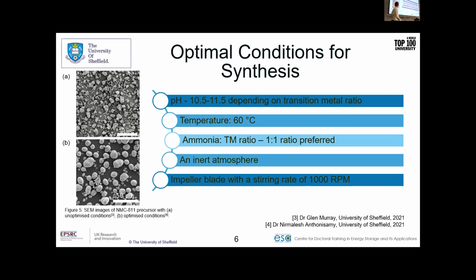And finally, in order to ensure that we provide enough shear forces to prevent clustering of these spherical particles, we like a nice impeller blade stirring rate. We've optimized this at about 1,000 RPM throughout multiple literature sources, as well as what we've found in the lab. And this allows the particles to be mixed and broken up enough so that it doesn't form too many clusters. There's maybe a couple of clusters here and there, but it's a lot more uniform across the population.